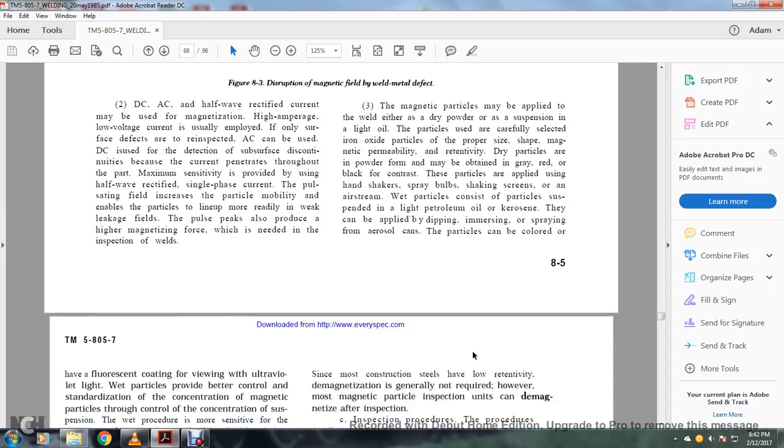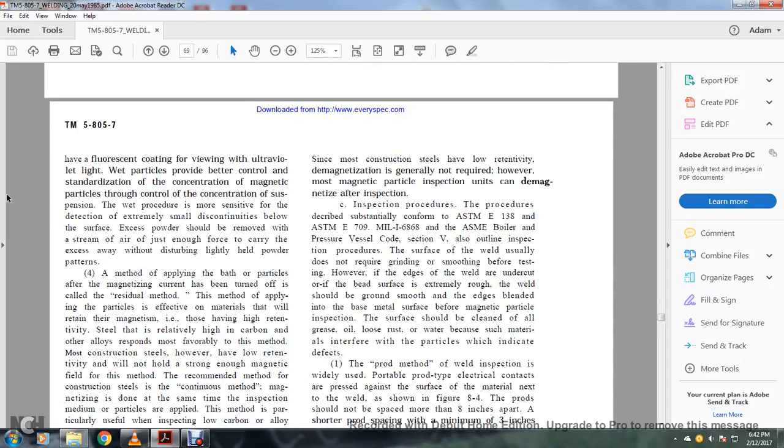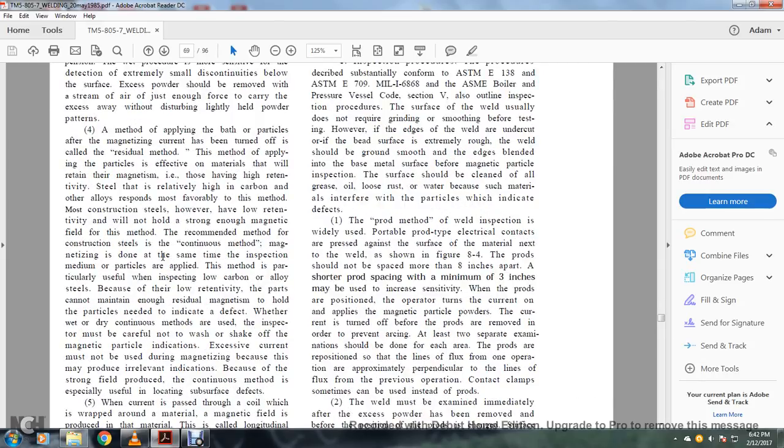These particles can be colored or have a fluorescent coating for viewing under ultraviolet light, and they provide better control or standardization of particle concentration through control of the concentration of the suspension. The wet procedure is more sensitive for direct detection of extremely small discontinuities below the surface. The excess powder should be removed with just enough air stream to carry off the excess without disturbing the light powder patterns.